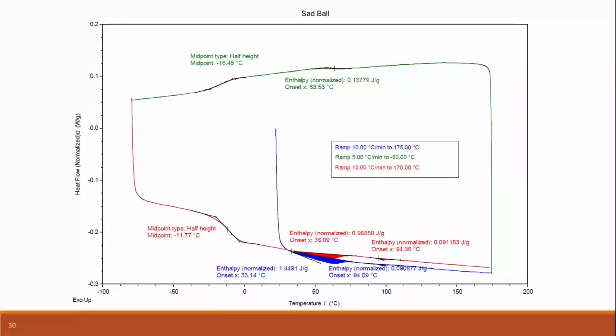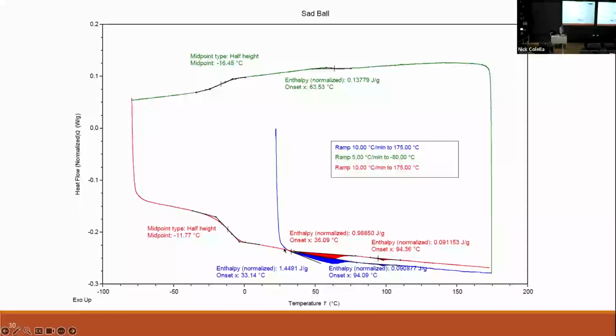What happens for the sad ball? We have a little bit more of an interesting curve here. So again, the blue curve is the first heating cycle. We see kind of a broad melting type transition starting at about 33 degrees. We cool down, we see kind of a broad crystallization, starting again at 63 degrees.